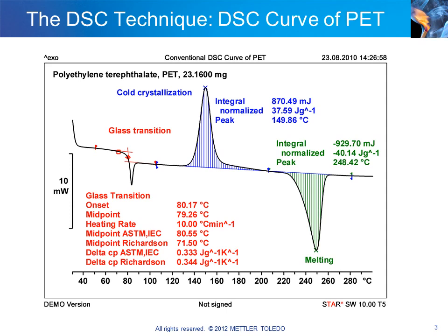This slide shows a typical DSC measurement curve. It was obtained by heating a sample of amorphous polyethylene terephthalate, or PET as it is called, at 10 degrees per minute. The initial startup deflection lasts about 30 seconds. After this, stationary conditions are reached and the measured heat flow is determined by the heat capacity of the sample. Various thermal events occur as the sample temperature increases. First, we see the glass transition accompanied by an enthalpy relaxation peak at about 80 degrees Celsius. This is followed by an exothermic, so-called cold crystallization peak with a maximum at about 150 degrees. In this process, part of the amorphous PET crystallizes from the strongly supercooled melt. Finally, the PET crystals melt and produce an endothermic melting peak in the range of 220 to 270 degrees.